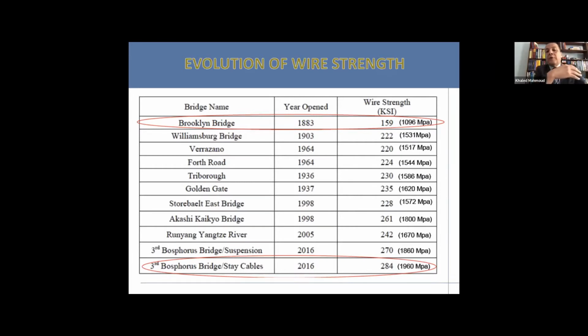So for the Golden Gate, it went up to 1620 megapascal. For the Akashi, it jumped to 1800 megapascal. And then when we constructed the third Bosphorus, we used the 1860 for the main suspension cables. And for the stay cables of the third Bosphorus, we used 1960 megapascal. There are suspension bridges that are being built today that are using 1960 megapascal for the main span wire, for the main cable wire.